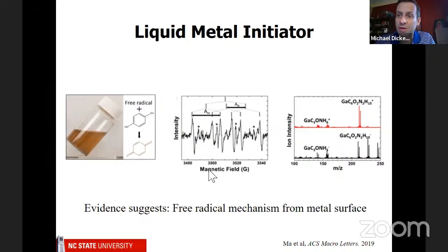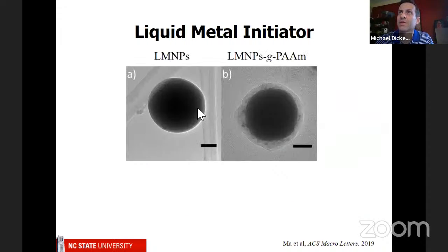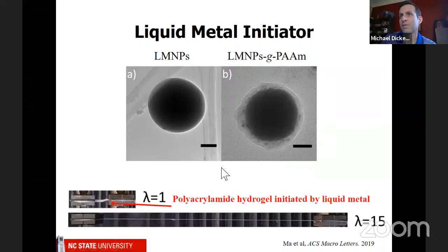So perhaps the best way to convince yourself is to actually look at the particles. And so this is a liquid metal nanoparticle, and you can see it here. It's sitting on a piece of graphite, which is what this other stuff is here. And it's kind of boring. It's just a sphere. Now, if we do this with the monomer, which is called acrylamide, a material that's used in contact lenses, you'll see that there's this polymer on the surface of the particle. So again, we don't completely understand it, but we do think that the gallium itself is causing the polymerization to initiate.